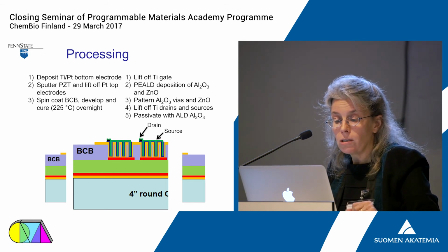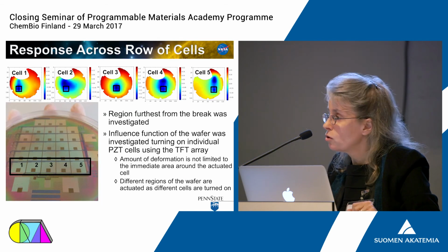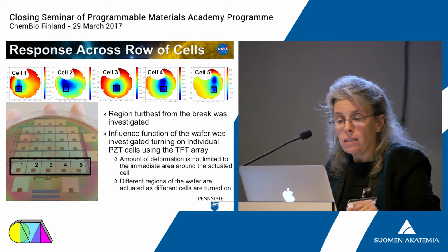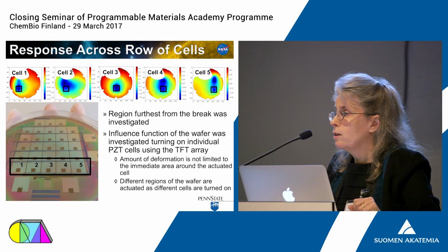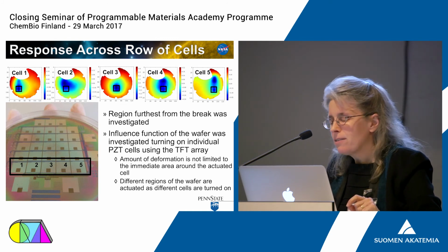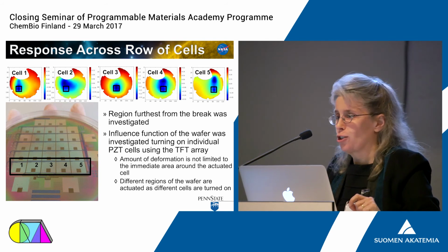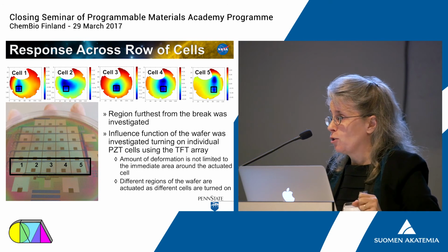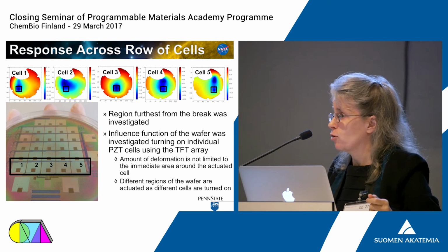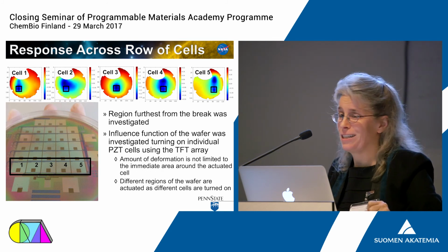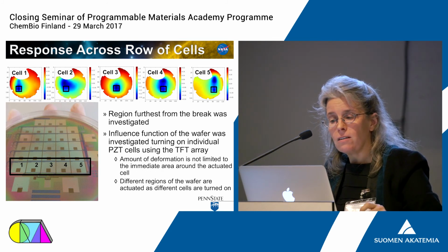We actually built an electrostatic discharge protection circuit down here in the zinc oxide. And we sent this off to our collaborators. We were very proud. When they mounted it in their mounting rig, they actually broke a piece of the substrate. Alas, they broke it on the side opposite to where we had our electrostatic discharge protection circuit. And when you break something, you stress it. And we just took a material that converts between mechanical and electrical energies, and we stressed it. So we partially damaged the electronics as we did this. So I don't have a perfect set of data.